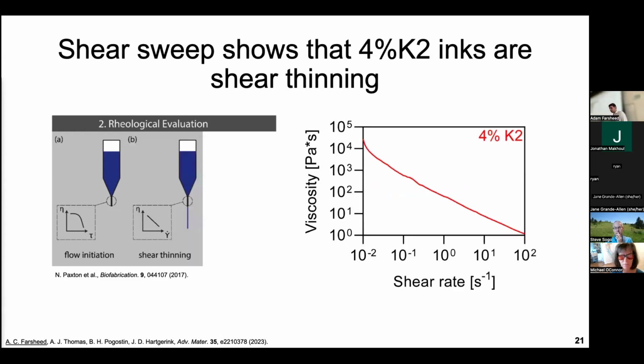The second property that's also very similar to this first one is that our material is shear thinning. This is a property that's also important for a lot of food products. And in this test, what we're doing is we're basically spinning the parallel plate faster and faster and faster, and we're measuring how viscous that material is. And what we want to see in this test is that it has this negative slope. It's hard to think about these material properties a lot of times, but what I think of this as is the opposite of quicksand. So quicksand, if you try to pull, it's going to get much harder. This is the opposite. If you try and pull, it's going to get easier and easier.